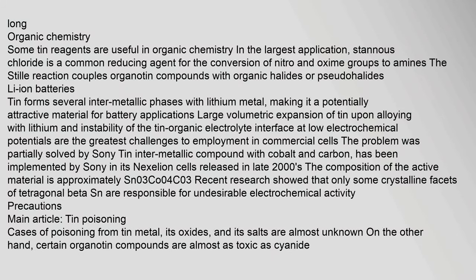In organic chemistry, stannous chloride is a common reducing agent for the conversion of nitro and oxime groups to amines. The Stille reaction couples organotin compounds with organic halides or pseudohalides. Tin forms several intermetallic phases with lithium metal, making it a potentially attractive material for battery applications. Large volumetric expansion of tin upon alloying with lithium and instability of the tin-organic electrolyte interface at low electrochemical potentials are the greatest challenges. This was partially solved by Sony, whose Nexelion cells use a tin intermetallic compound with cobalt and carbon, with active material composition approximately Sn0.3Co0.4C0.3.